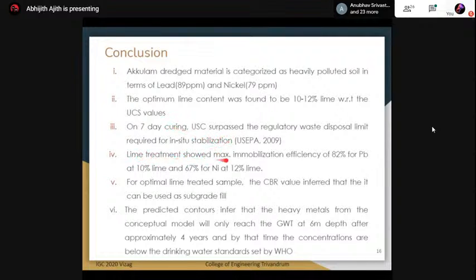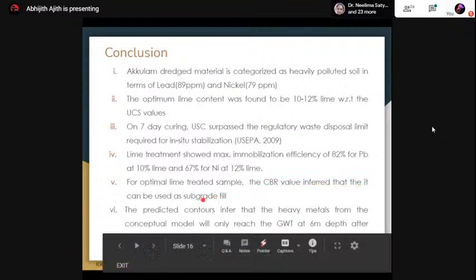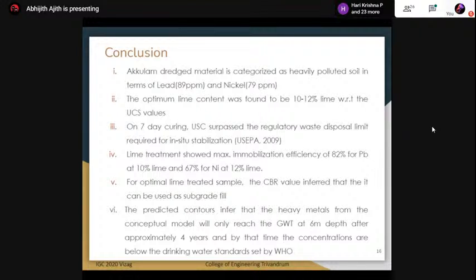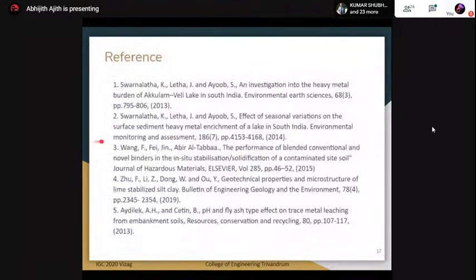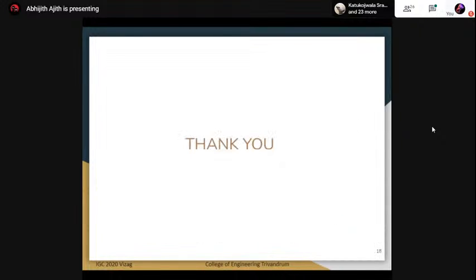And lime treatment showed that a maximum immobilization efficiency of lead at 82% could be achieved by about 10% lime, and for nickel, 67% of immobilization could be achieved by 12% lime. So for the optimum lime treated, the CBR value inferred that it could be used as subgrade fill, and the predicted contour inferred that heavy metals from the conceptual model will only reach the groundwater at 6 meter depth after approximately 4 years, and by that time the concentrations are below the drinking water standards set by WHO and also IS standards. So these are the important reference of the paper, and thank you.